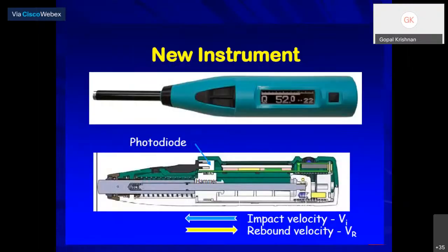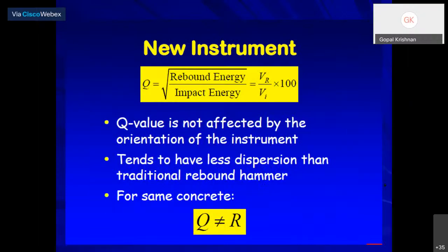Now let us see the new hammer. Now they are talking about the Q value. Generally, the R value is used for manual or digital instruments. But the Q value is more electronic, having a better correlation coefficient of 0.97 compared to 0.84 for the R value. So you will get more accurate results with the latest hammer's Q value. The Q value is not affected by the orientation of the instrument, so we don't need to do the correction. It tends to have less dispersion than the traditional rebound hammer. Anyway, the Q value is not comparable with the R value.